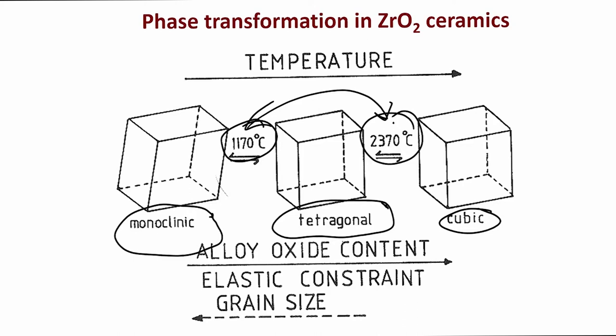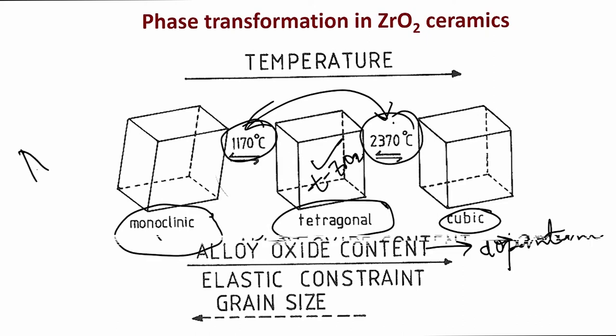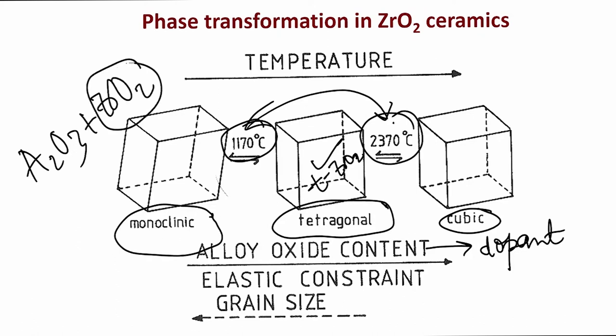Now, as I said, this alloy oxide content is nothing but dopant content. So, if your dopant content increases, it means that this particular tetragonal zirconia phase is stable at room temperature. And if the elastic constraint in the matrix also increases, for example, if you add zirconia to an alumina matrix. So, you have pure alumina and then you add a little bit of zirconia in the alumina matrix. So, these are the zirconia particles.